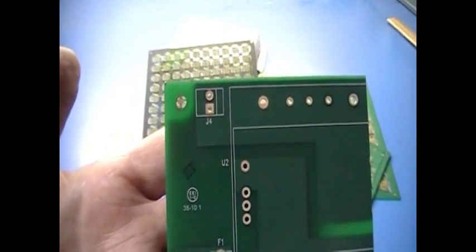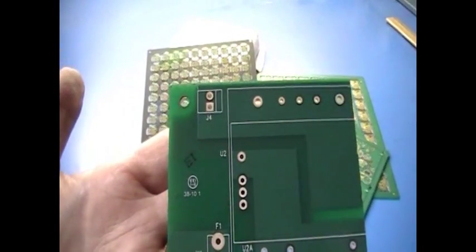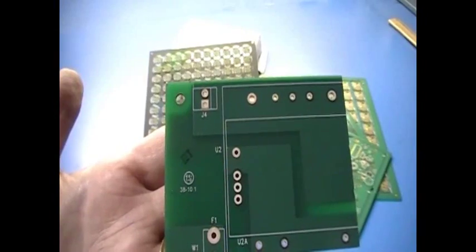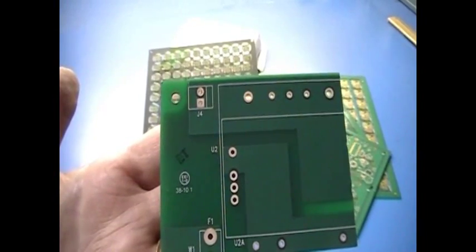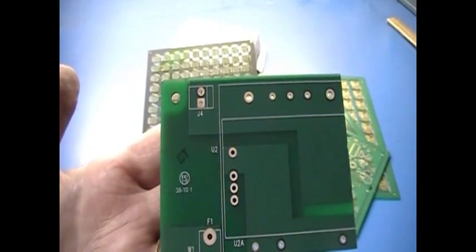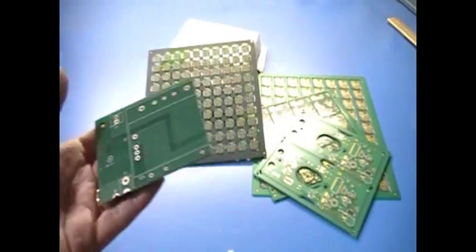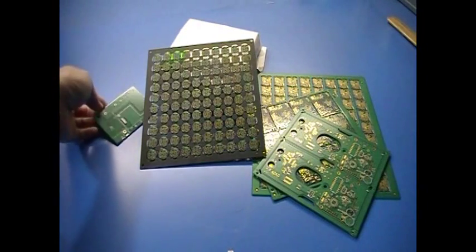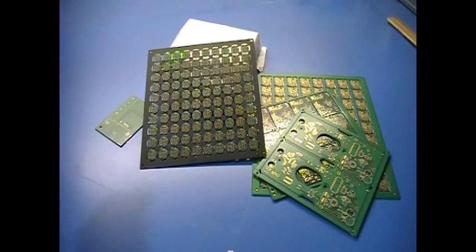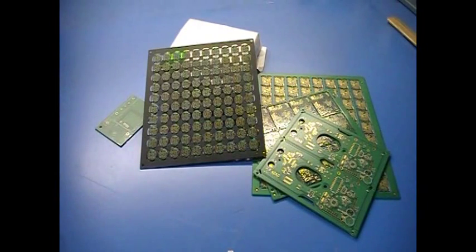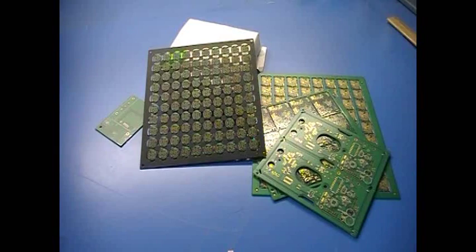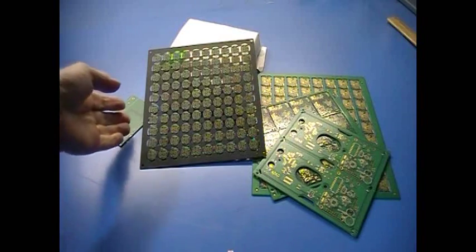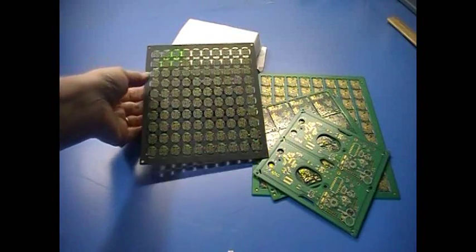Too much tarnish leads to lower quality solder joints and poor yields in PCB assembly, so you need to solder immersion tin boards within about 30 days. Immersion tin is a pretty good choice for high volume production, where you'll use large batches of boards very quickly.